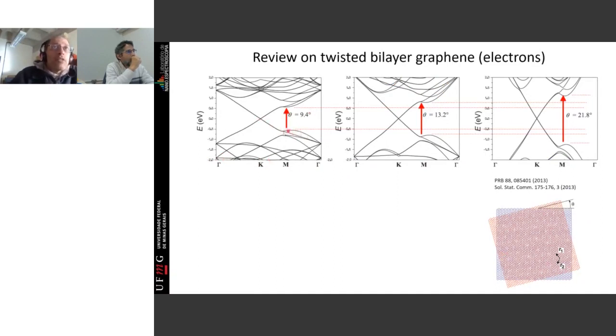And when you have a situation like this, that is, the band gets flat here with respect to this momentum axis, you have a strong, let's say, density of electronic states at this given energy, okay? And what we see is that if you rotate the angle, here the angle is 9.4, 13.2, 21.8, the distance in energy between these two levels increases.